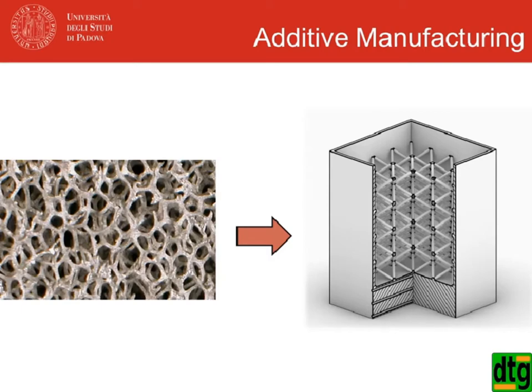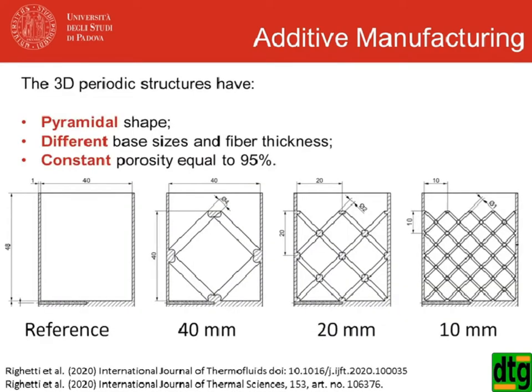Here we are. So we want to pass from a stochastic structure to a periodic structure. And here you have a typical box that we are studying. So here you have our work on 3D periodic structure. So we decided to study pyramidal shape because this shape and the arrangement you see in the picture below can be easily printed. And we decided to keep the porosity at 95% at the very beginning, but it can be easily changed, okay, and study the effect of the pore size. So we studied 10, 20, 40 millimeter of pore size.